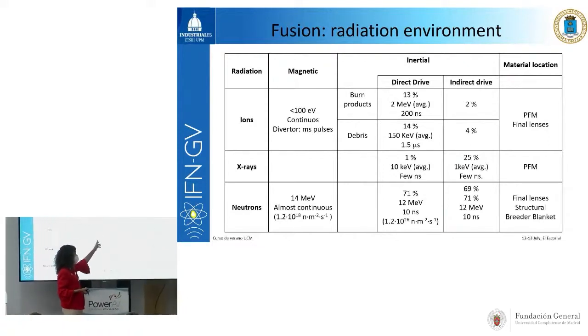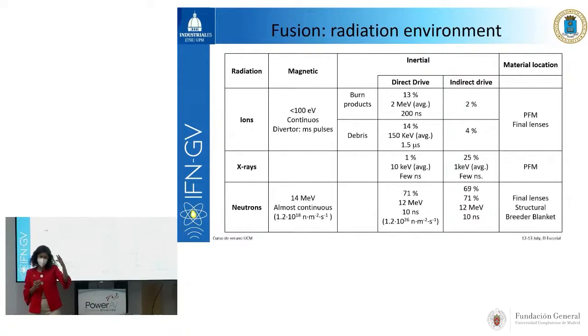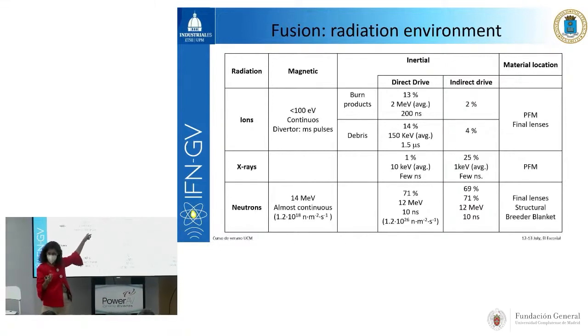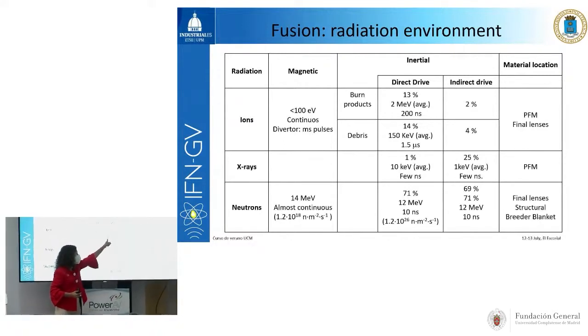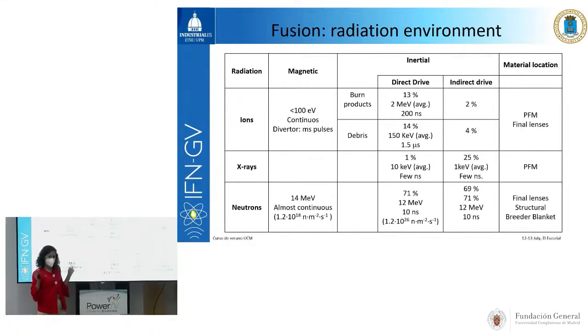And if we have debris, then the energy is lower, but still it's an order of magnitude higher than the one we have in the magnetic configuration. It's going to be 150 keV on average, okay? And this is going to be the pulse duration.